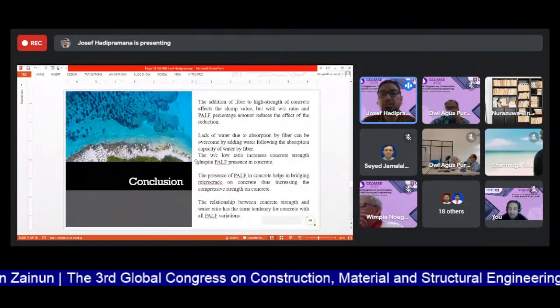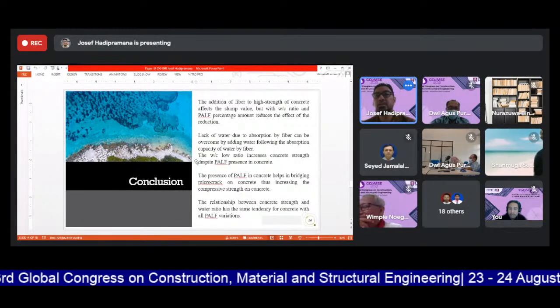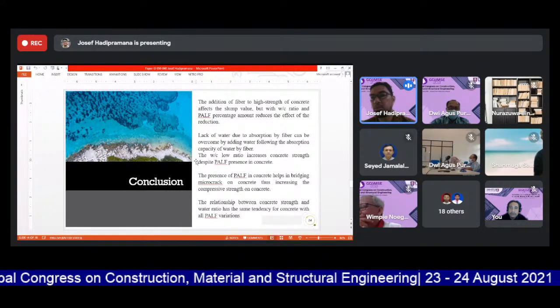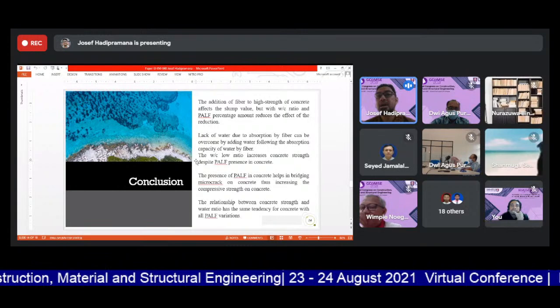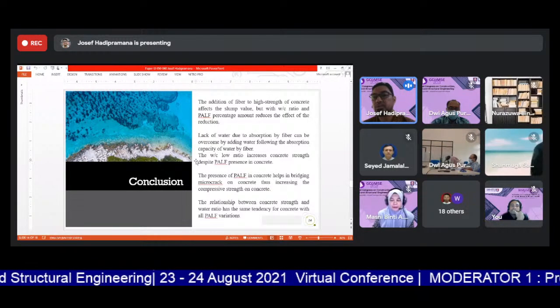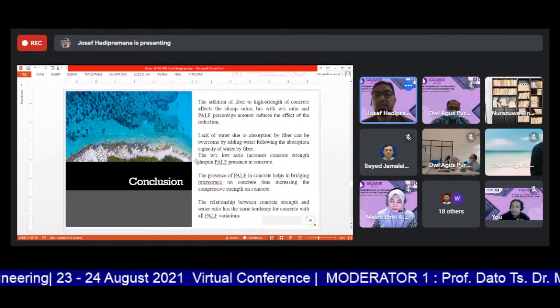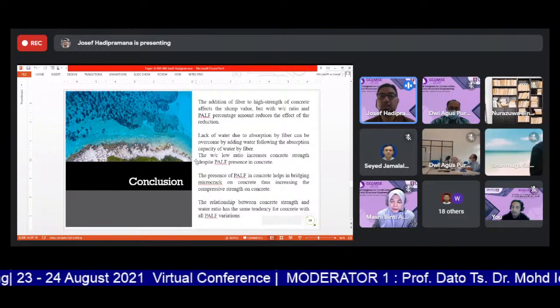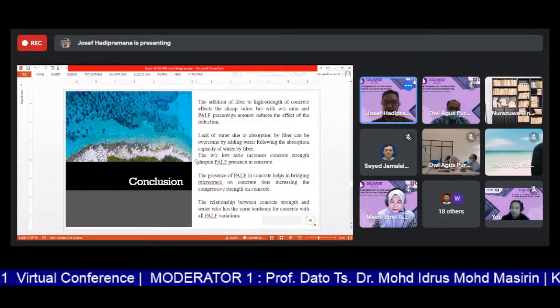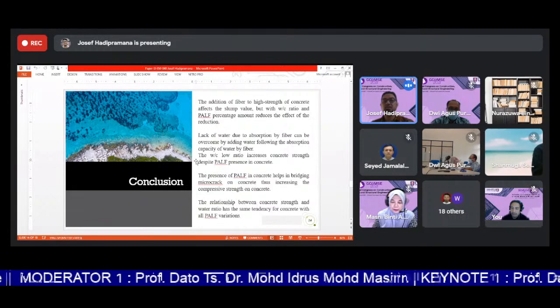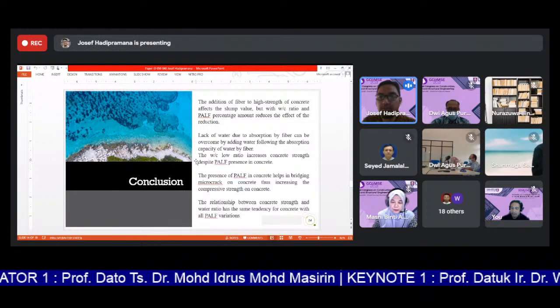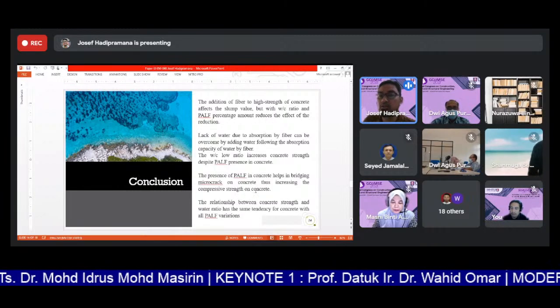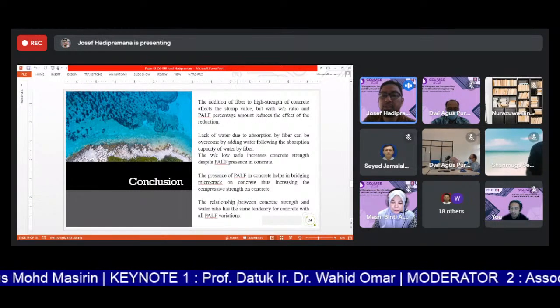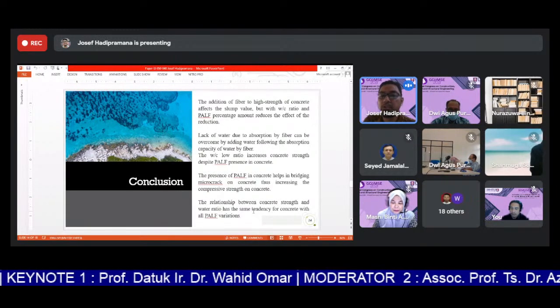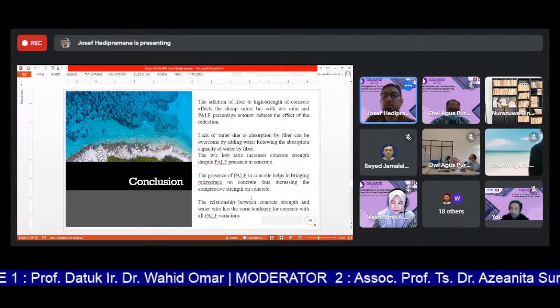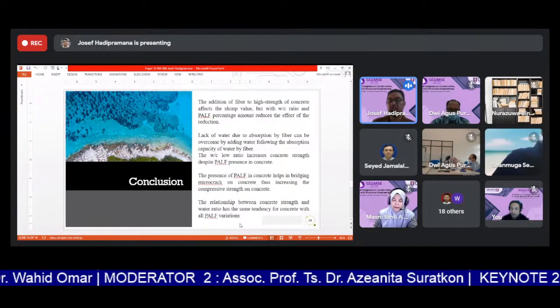So the conclusion of this study is the addition of fiber in high strength concrete affects the slump value, but with water cement ratio and PALF percentage amount, they reduce the effect of the reduction. Lack of water due to absorption of fiber can be overcome by adding water following the absorption capacity of water by fiber. The low water cement ratio increases concrete strength despite PALF presence in concrete. The presence of PALF in concrete helps in bridging micro cracks on concrete, thus increasing the compressive strength of concrete. The relationship between concrete strength and water ratio has the same tendency for concrete with all PALF variations.